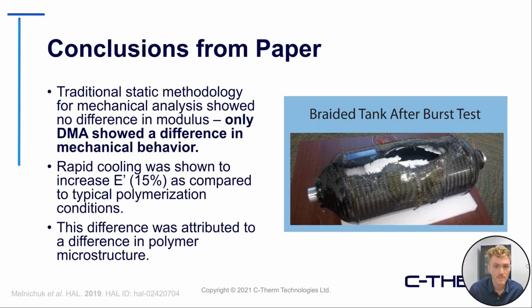So some of the conclusions from this paper are that typically when you're designing these composite materials that are designed to be under dynamic stress and dynamic strain, traditional static methodology is not adequate enough for us to look at the modulus. And only DMA itself is able to elucidate differences in the microstructure of the polymer material. So they were able to elucidate a better technique for creating these Type 4 hydrogen storage containers, which were 15% stronger than their typical batches. And this was attributed to a difference in the microstructure of the polymer, which was elucidated by DMA.